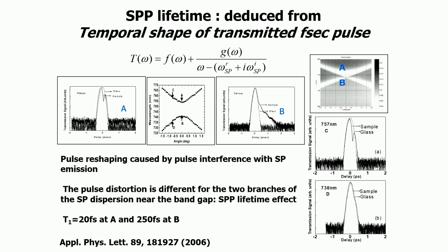In the initial work which we did, we showed that if you launch a short pulse and make it interact with this grating structure, and you look at the dynamics of the pulse reshaping, we deduce that the pulse reshaping depends on the plasmon dispersion. For example, the A and B points shown here are the upper and the lower bands, and they have different line widths or different lifetimes.